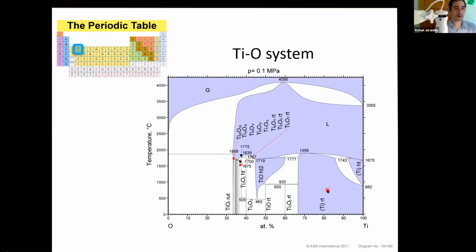You expose a material to oxygen gas, and there's some catalytic process by which the oxygen gas splits into oxygen atoms at the surface, and the oxygen atoms diffuse into the metal. It's almost certainly not dissolving O2 molecules. Metals that do dissolve oxygen are the basis for a lot of interesting technologies, but we won't have time for that. Any other questions on these phase diagrams and interpreting them or applications and so forth before I move back?